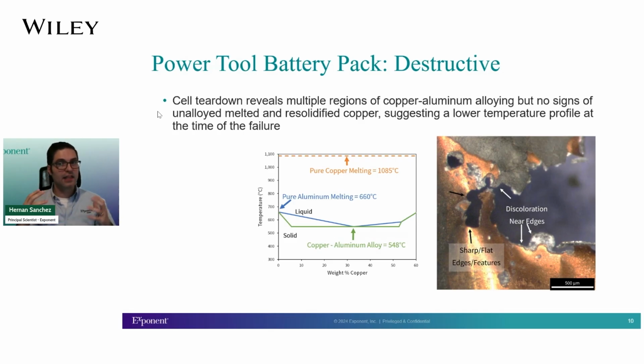So once again, this is a piece of the puzzle that tells us that we were not able to find in the remnants anything that told us that the cell had gone over 660 degrees Celsius, which is what you would need to melt the aluminum and to start the alloying process. Or you can even do it a little bit lower than that too. But we were not talking about temperatures over 1,000 degrees Celsius, which is sometimes more associated with an internal cell short. So that, combined with all the other information we were gathering, leaned very much towards some type of external heating causing the cell failure.